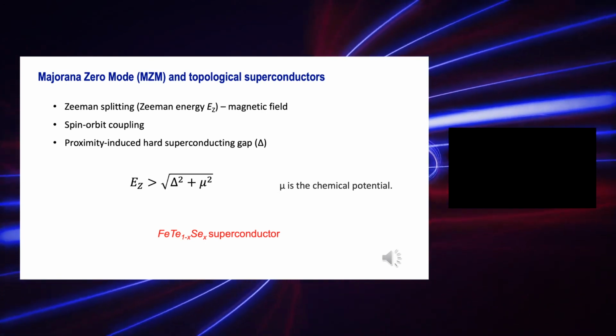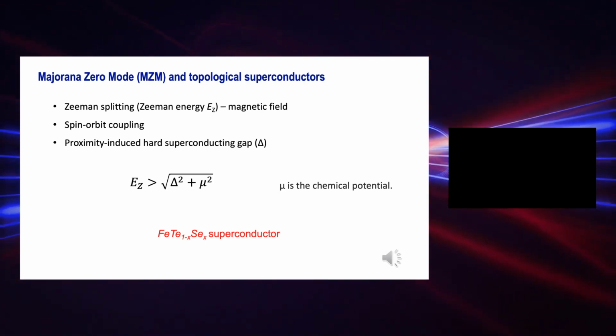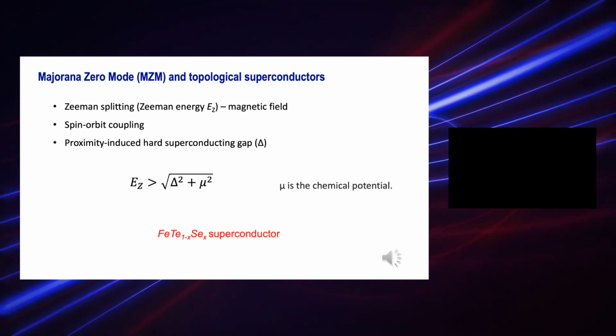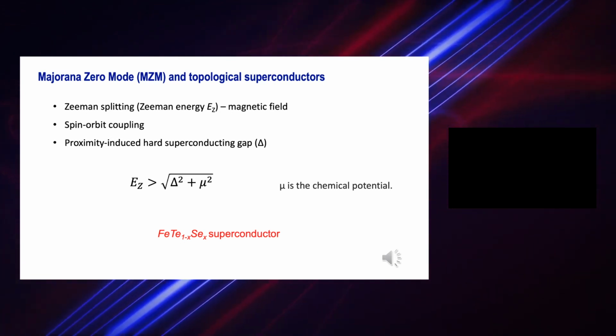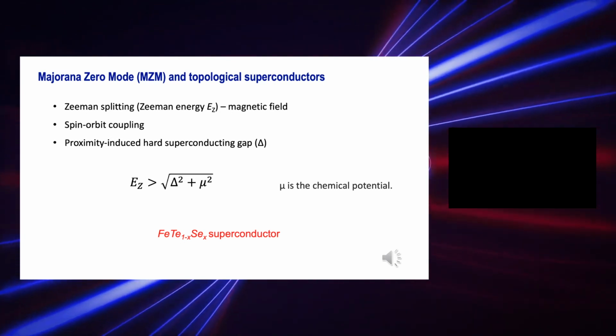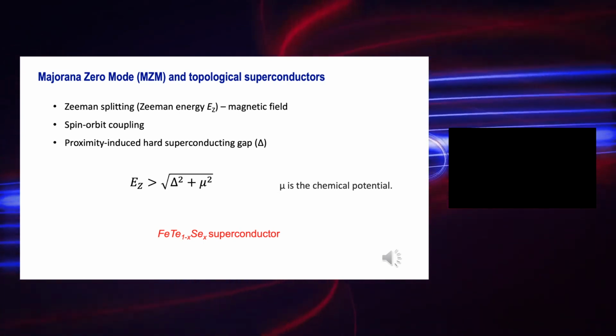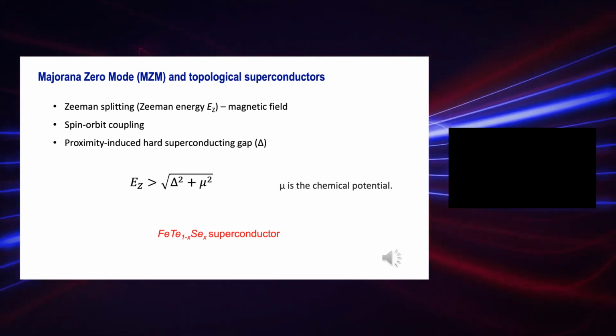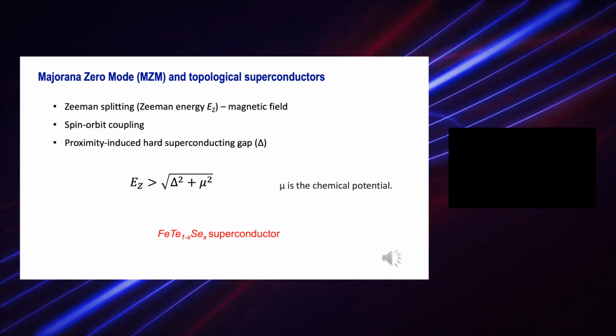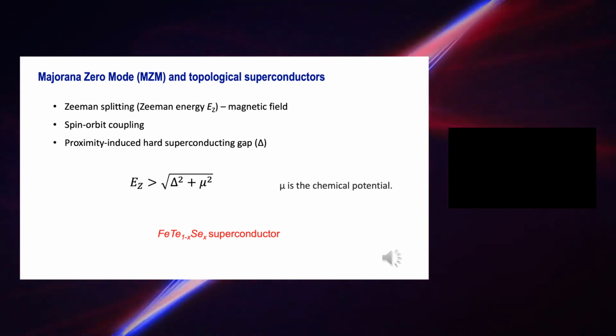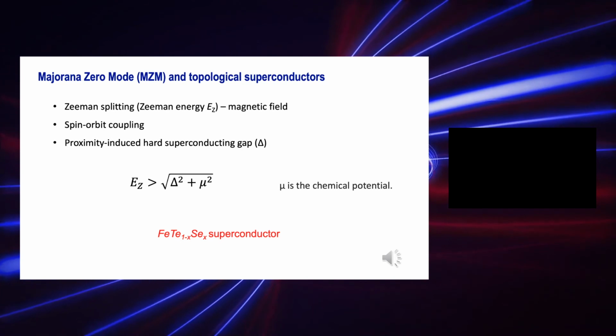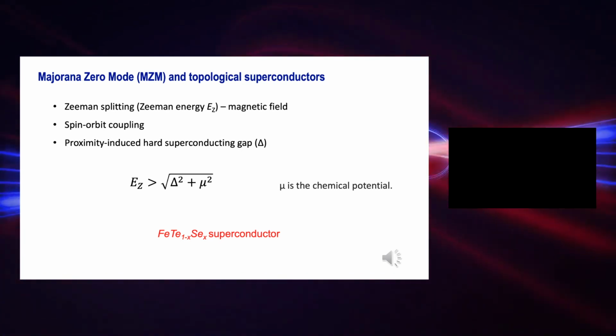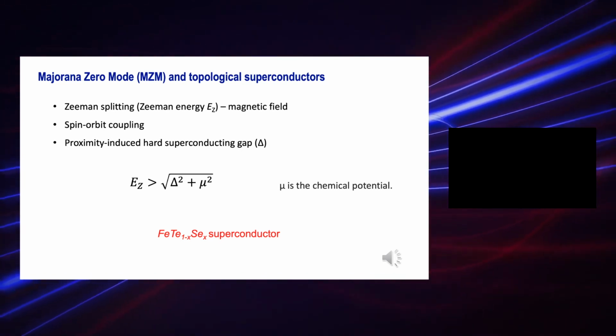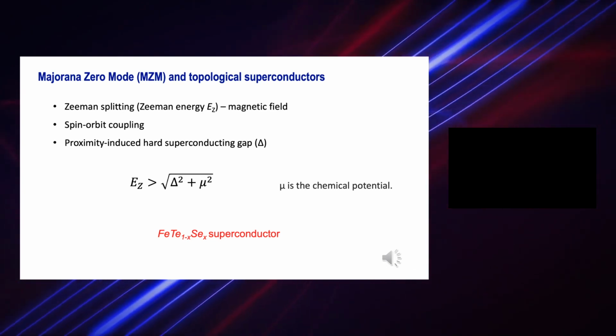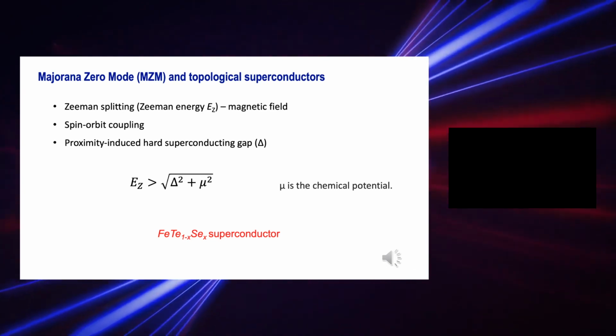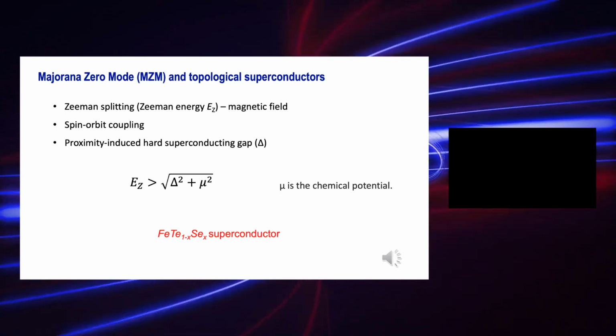Now you have tellurium, which is a heavy metal, producing a strong spin orbital coupling. You have the superconductor producing the gap. And also possibly you have some of the iron impurities producing the intrinsic magnetic field there. Now the trick here is that you have to reduce the superconductor gap and also have a very small chemical potential so that the Zeeman energy will be bigger than the combination of both. And this is the research where you really have to go in for.